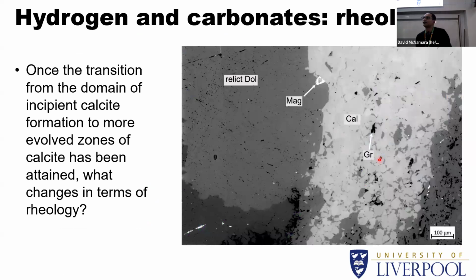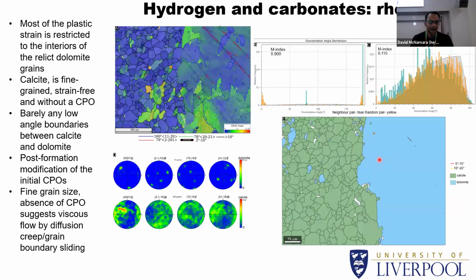The final bit is where we find a lot of calcite in our sample. So these wider zones with a lot of calcite, graphite, and magnetite separating zones of dolomite. If we look at the EBSD maps of this domain, then we see that the CPO of calcite is super weak. It's widely distributed without any particular preferred orientation. A very low M index value for calcite as well. And this, coupled with an average grain size of 15 to 20 microns, suggests that the calcite underwent viscous flow by either diffusion creep or a component of grain boundary sliding in this domain.